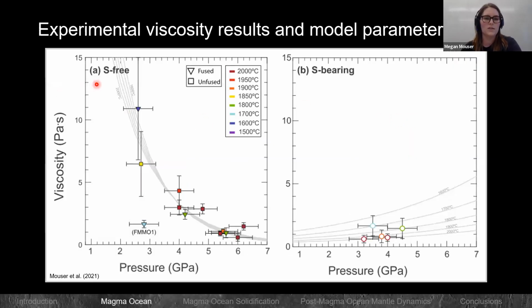So panel A is the sulfur-free, and if we start there, we can look at the data, and what we can see is that we have a temperature and pressure sensitivity, where the low temperature, low pressure experiments have the highest viscosity, and as we increase in PT conditions, we decrease in viscosity. So it's a fairly nice relation that we see within this data set.